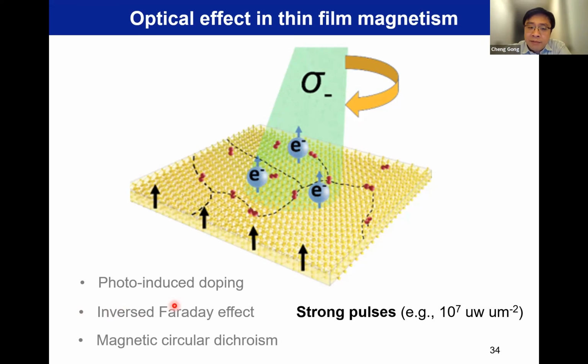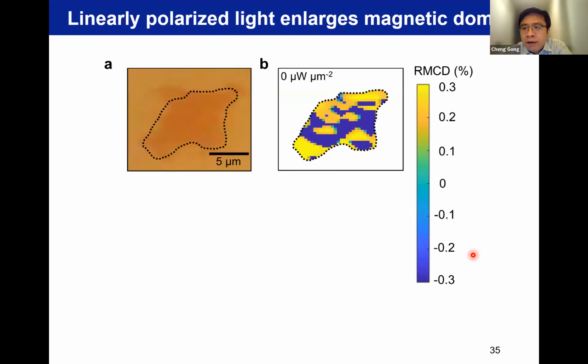But by either mechanism, you have to use a strong ultra-fast laser on the order of 10^7, 10^8 microwatt per micrometer squared, sometimes 10^6, depends, but it's a similar order of magnitude. So here, what I did is totally different from this traditional magnetic switching. I'm not working on switching here.